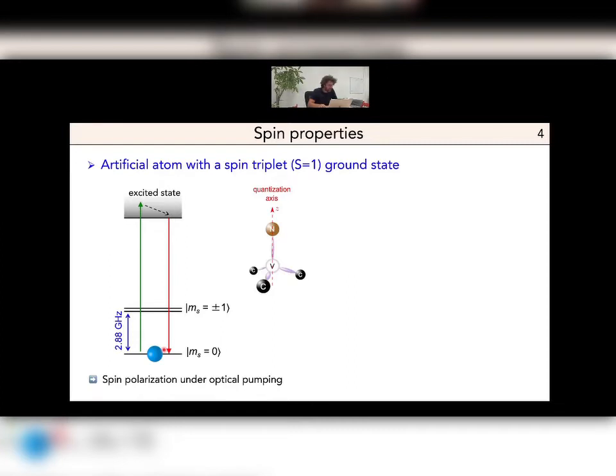The second property is that the NV defect exhibits a spin-dependent photoluminescence signal. And if you want a nice picture of the NV defect, you can just consider that the ms equals 0 state is bright. There will be a lot of photons emitted out of this state, while ms equals plus minus 1 are dark states. Fewer photons are emitted when these states are populated.